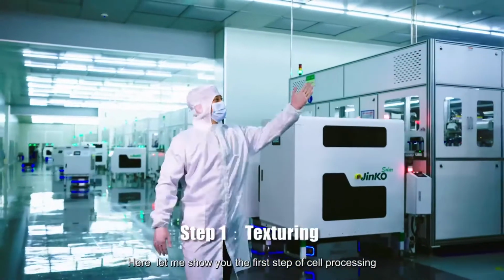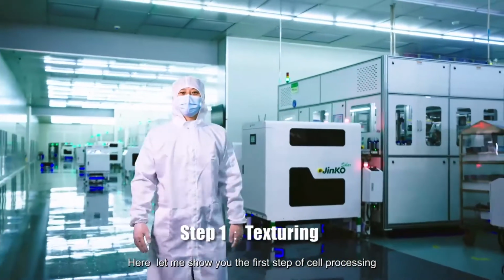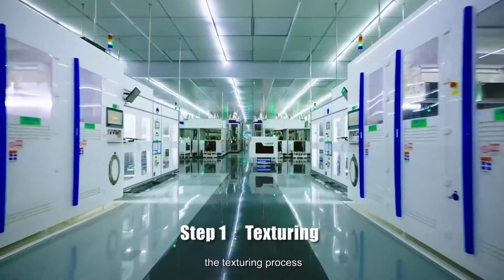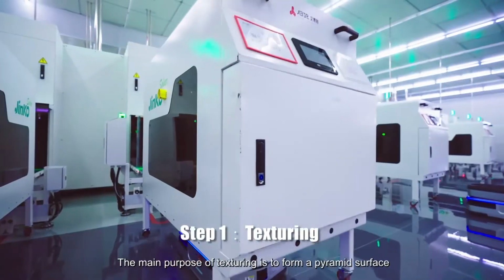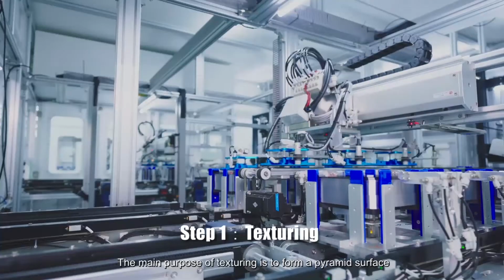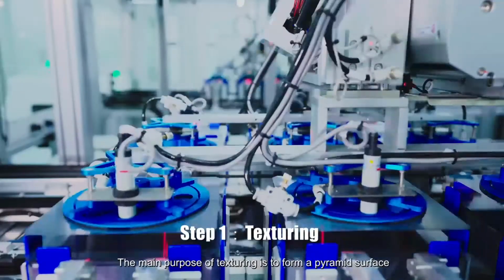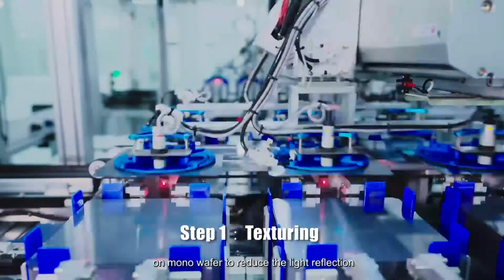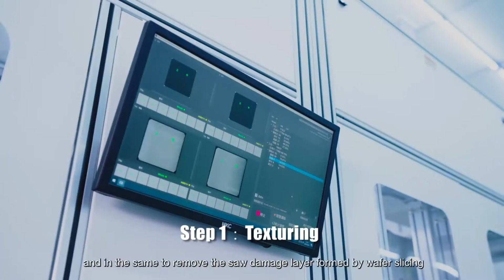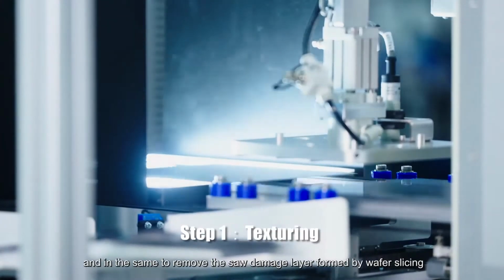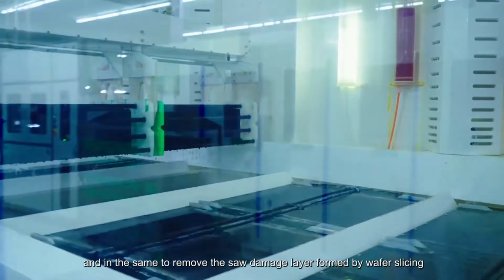Here, let me show you the first step of cell processing, the texturing process. The main purpose of texturing is to form a pyramid surface on the mono wafer to reduce the light reflection and at the same time to remove the saw damage layer from wafer slicing.